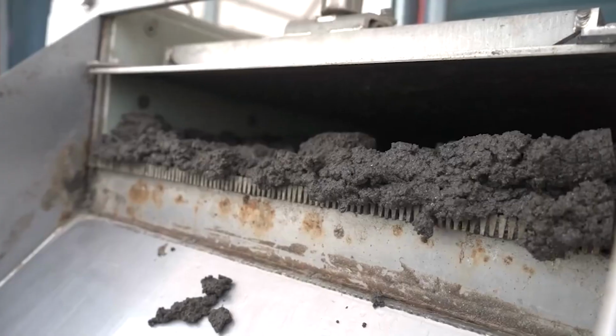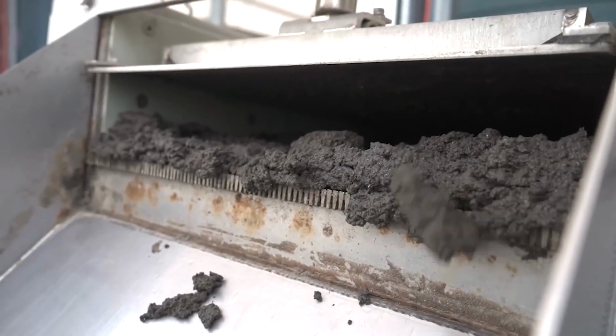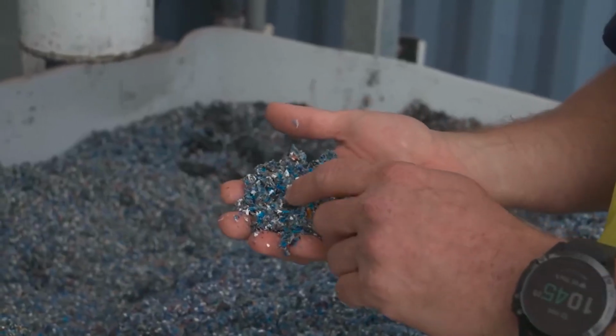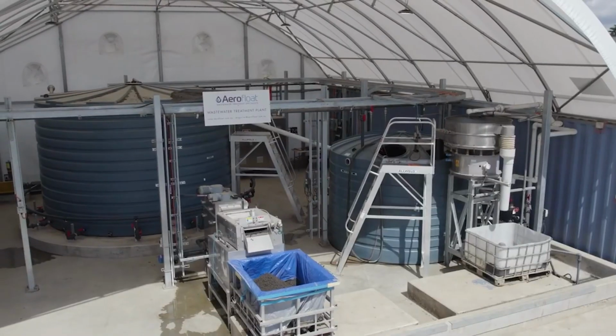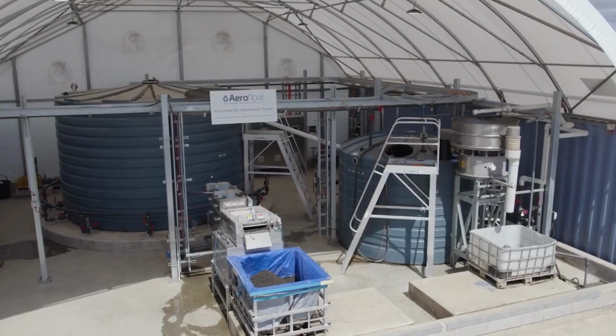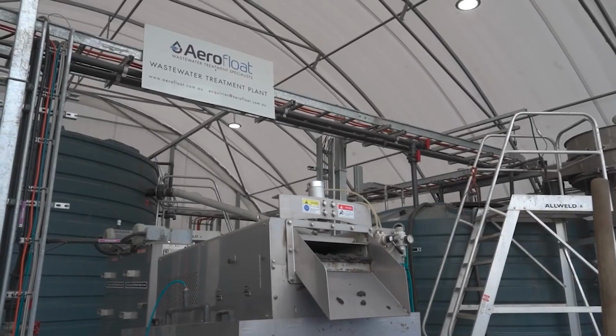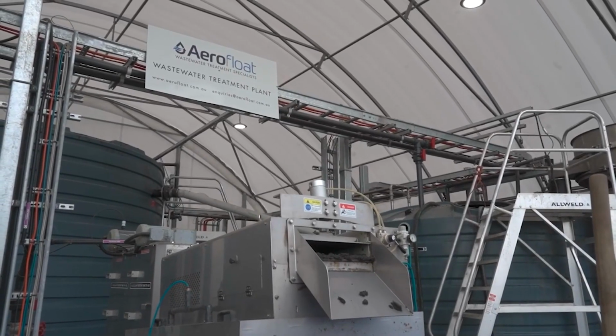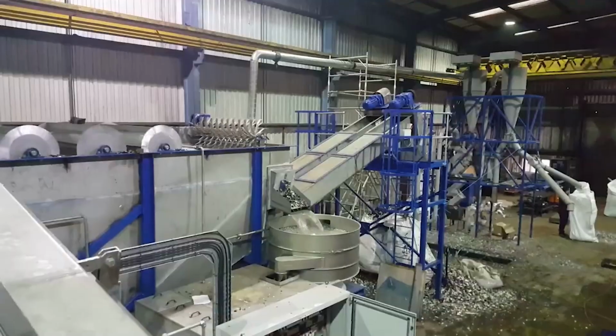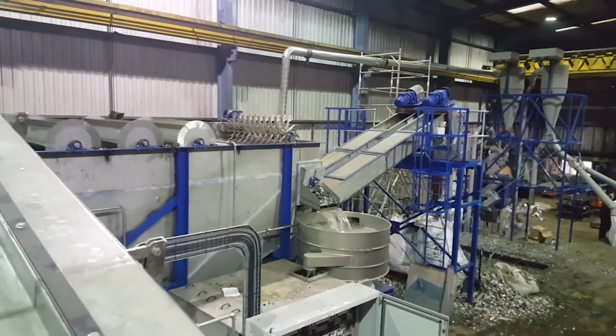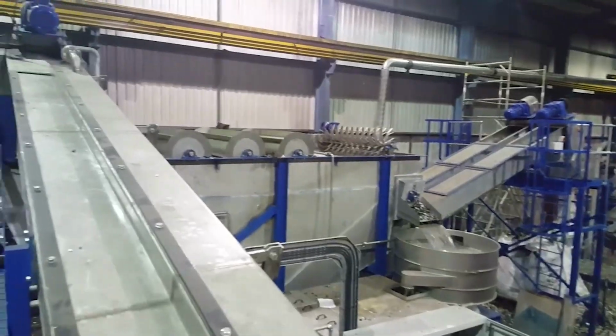Then, density-based separation using the float sink principle. Heavier plastics like PET sink to the bottom, while lighter plastics, HDPE and PP, float to the surface. This physical separation significantly improves downstream recycling quality. After separation comes drying through centrifugal systems using hot air to remove moisture.